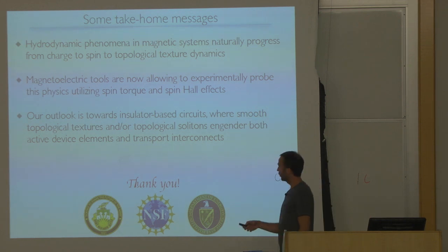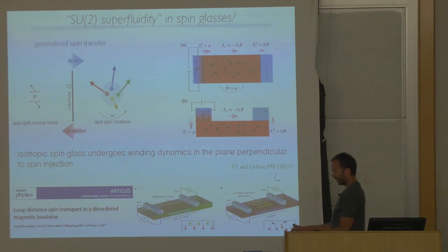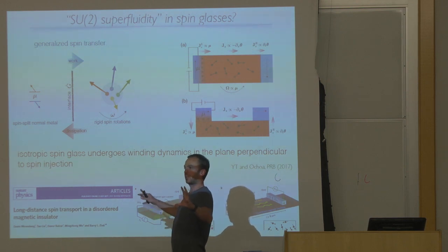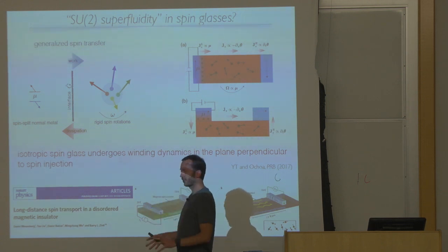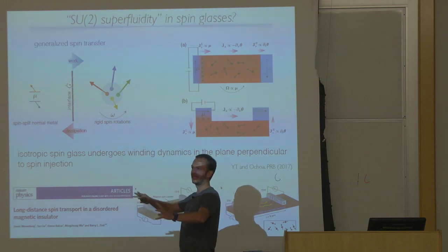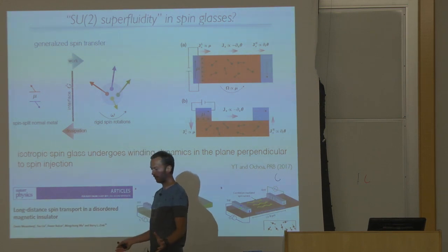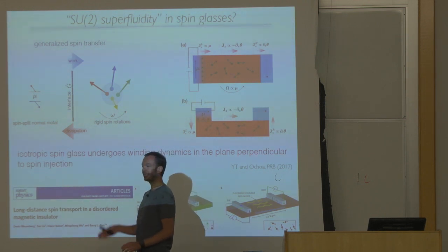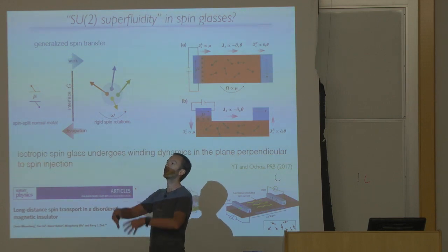Yeah. So, okay, thank you for asking, so we can talk more about this. What is a spin glass, right? Let's just imagine some amorphous material with, let's say, a random exchange interaction. So there's no simple ground state, but when the system equilibrates, there's no long-range order whatsoever. There's no magnetic order. At each point the orientation is random, but it's frozen. That's the key. So the spin orientation is random, but locally frozen.